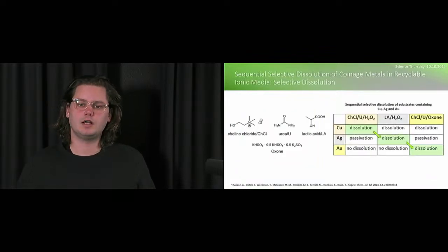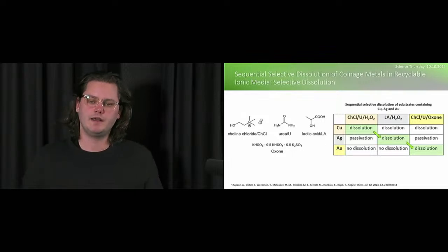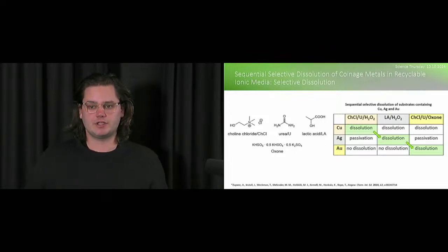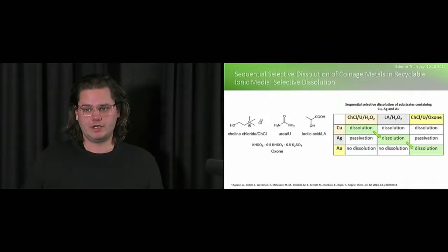So we try to design this sequential selective dissolution of coinage metals in this recyclable ionic media. What we were trying to do was, we chose one of the more famous examples of deep eutectic solvents, which is choline chloride urea. You can produce this deep eutectic solvent by using choline chloride and urea, and you get this very viscous liquid. And we were playing around also with lactic acid.